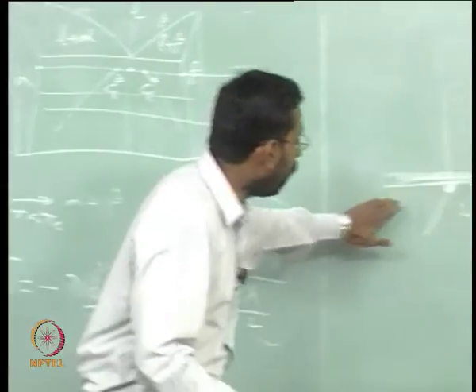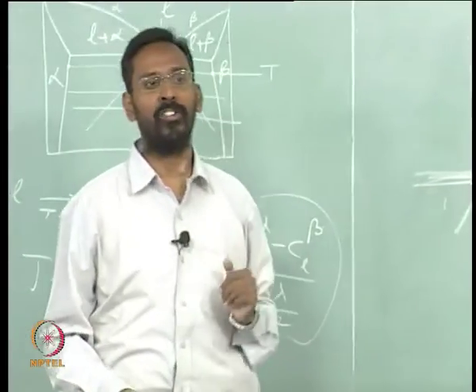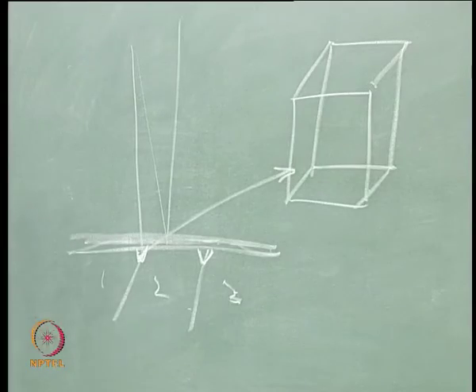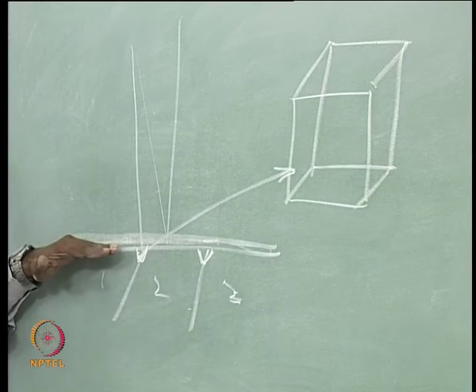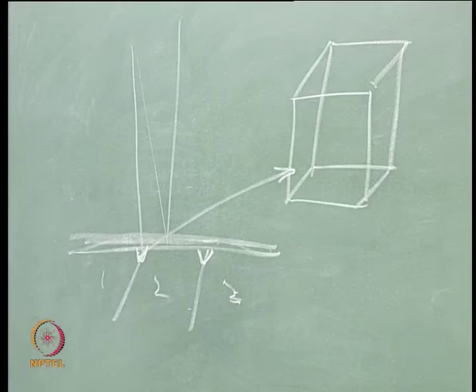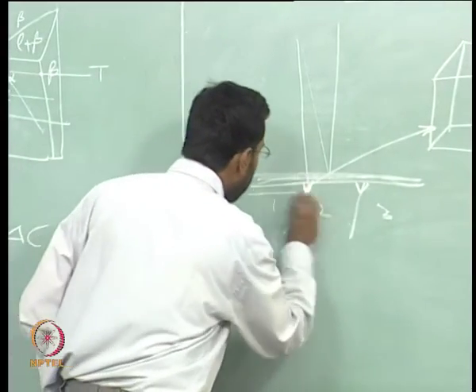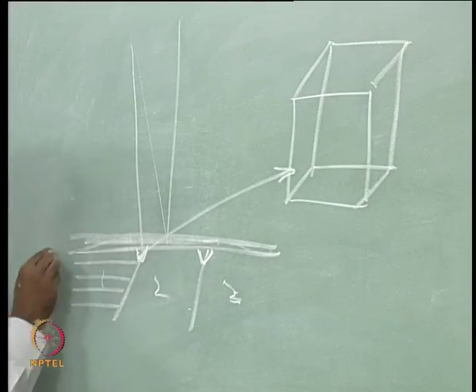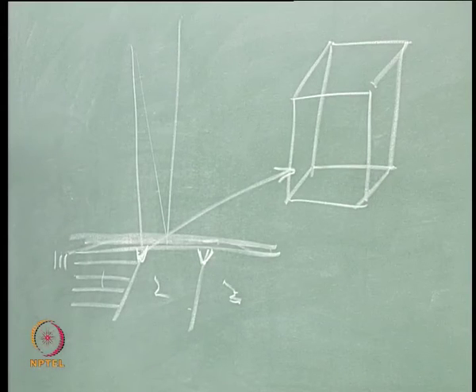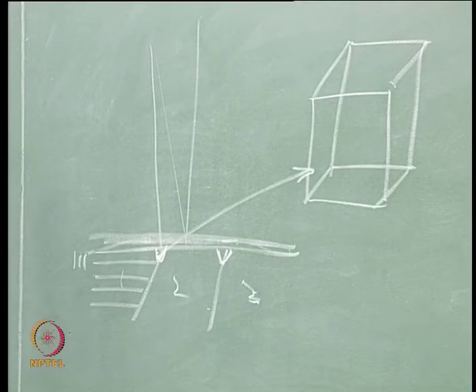Similarly, the grains also dissolve differently because the atomic planes parallel to the surface are not the same for grain 1, grain 2, and grain 3. For example, in grain 1 the plane parallel to the surface may be the 111 plane, but in grain 2 it is impossible to have the 111 plane parallel to the surface.